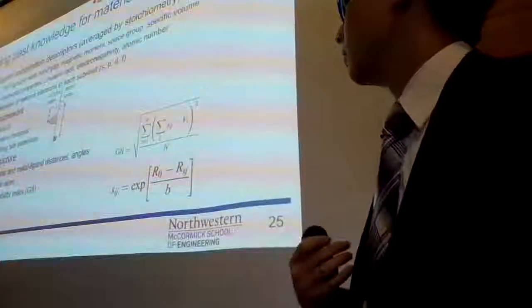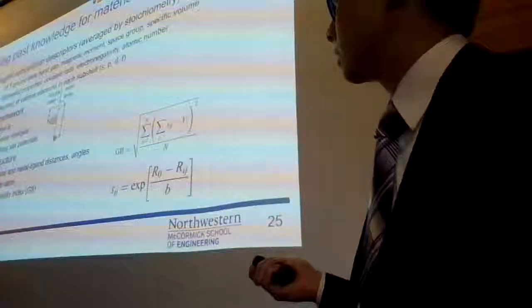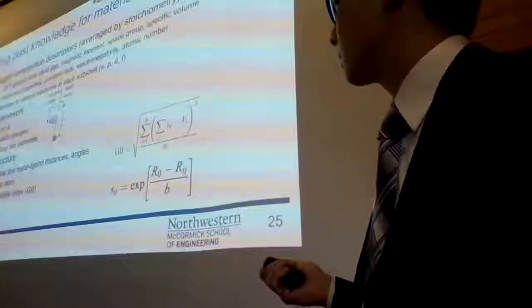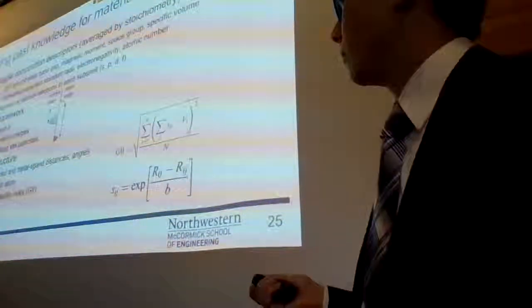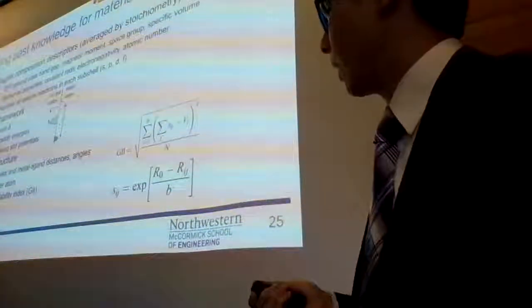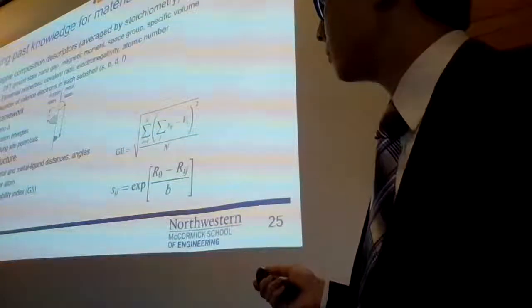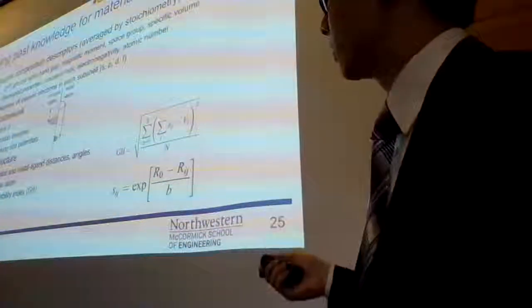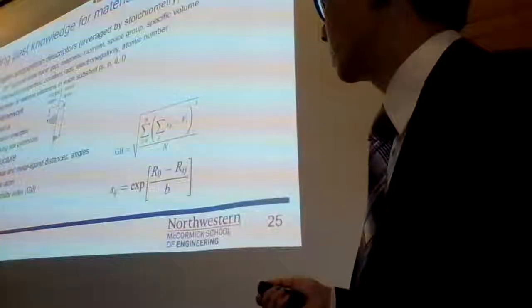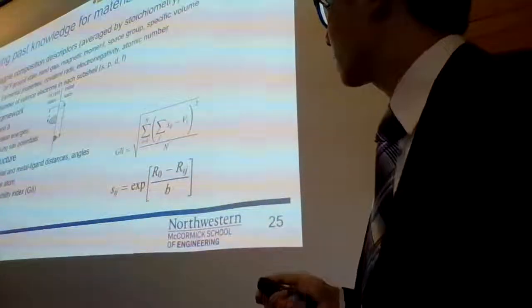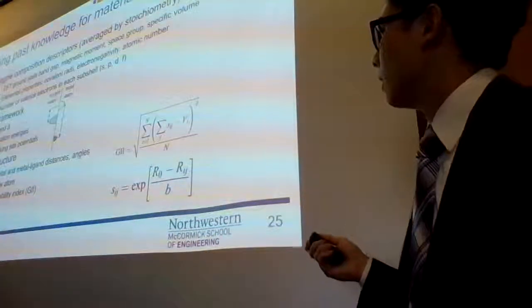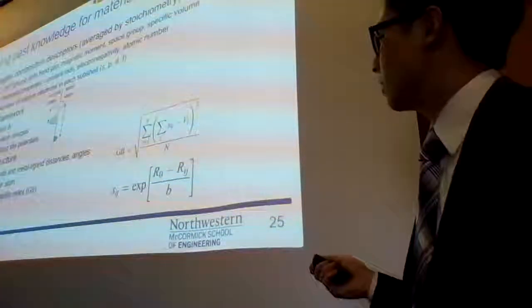transition. I have to be able to distinguish between things with dissimilar metal-metal and metal-ligand distances, bond angles as well. Related to the density, I have the volume per atom of that structure. And some other structural features that don't appear on this list because they would take up too much space, as well as this global instability index, which is based on sort of an average deviation of bond valence.